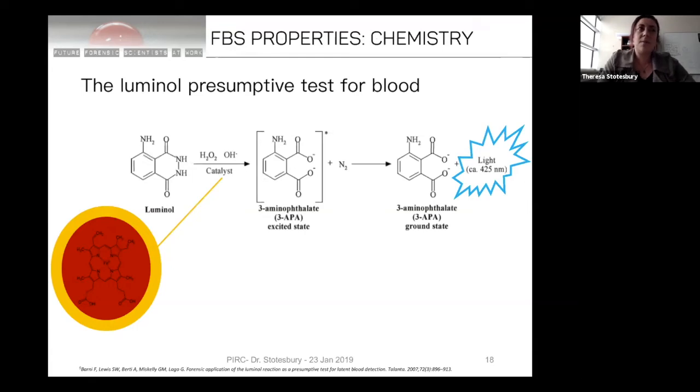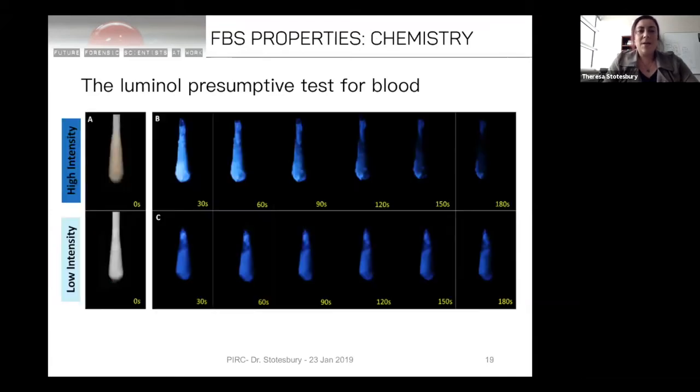So we spend a lot of time really optimizing the chemistry and really the kinetics of the chemiluminescent reaction. And have made a blood substitute for that. Here's just some examples of it glowing. This is our blood substitute at different dilutions here on the far left, the top being the higher concentration of the enzyme that we included in our polymer, down below a lower concentration, and we can see how the chemiluminescence emission intensity changes over time and changes as a function of concentration.